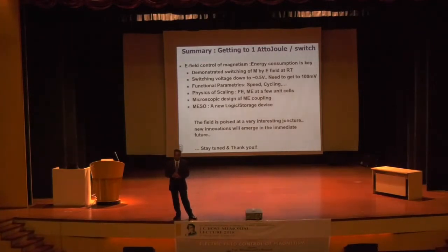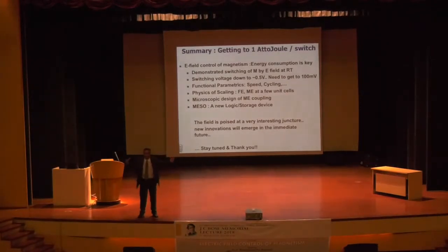I think bismuth ferrite is good because it's the only system which has the ordering parameters at high enough temperatures. So it's a robust material. You've got to be at room temperature, so that's no question. That's one reason. There are some negatives with that system because it distorts very strongly. I think we can tune it. I don't think we have tapped the limits of coupling mechanisms, and those artificial superlattices may be a pathway to much more effective coupling mechanisms.